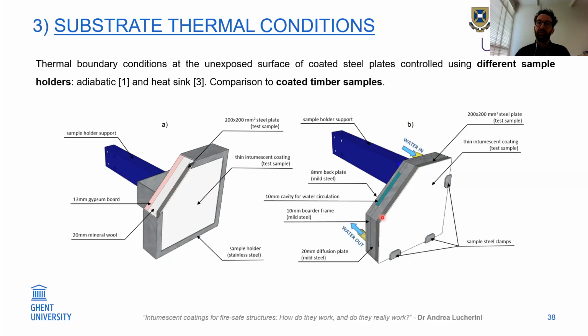Then I also developed a custom-made sample holder where I had my steel plate, and at the back there was another steel plate, and then a cavity where I could circulate water. You can see here water in and water out. There was a 10 mm cavity for water circulation and then another steel plate at the back. Mainly by controlling the water flow inside my cavity, I could cool down my plate at different rates. And I also compared this case with the same coating applied on a CLT or timber sample.